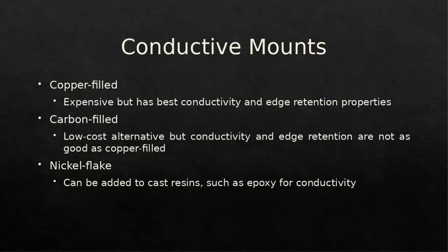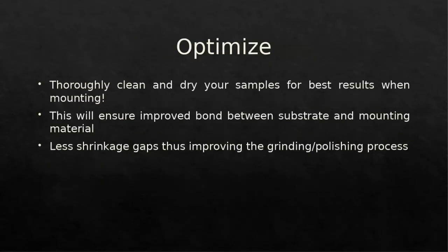I mean, there's nothing wrong with using carbon filled conductive mounts. And just in case your sample was huge and you had to use a castable epoxy resin, then you can add nickel flake to that resin, and that would help with the conductivity. Once again, not as superior as the copper filled epoxy mounts.